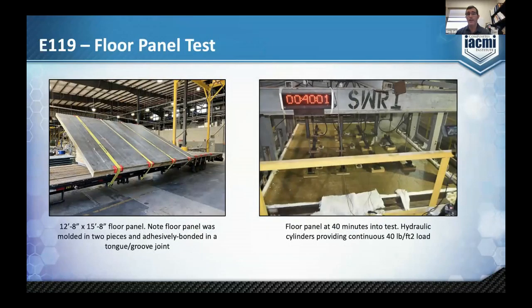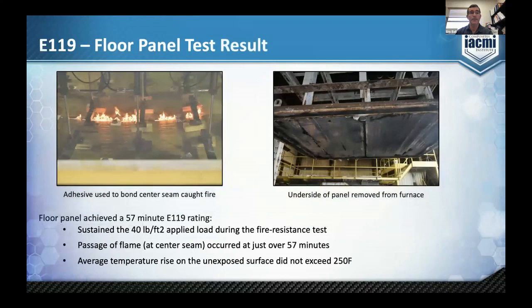And then here's a floor test. It's similar. It was loaded at 40 pounds per square foot during the furnace test. This test, unfortunately, we built this panel in 2 pieces and bonded it together, and it failed because of the adhesive we used in the tongue and groove joint. It would have passed an hour easily had we done that joint a little bit differently, or had built the panel all in one piece.